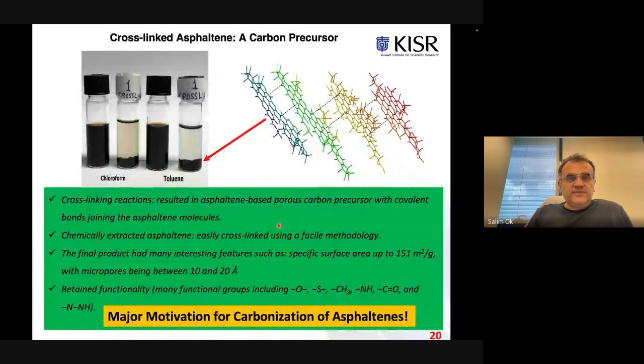And later on, as you can see here, we made a very simple visual inspection test. For example, we use chloroform and toluene, which are the solvents for raw asphaltenes. But when we switch to cross-linked asphaltenes, they are not soluble anymore.